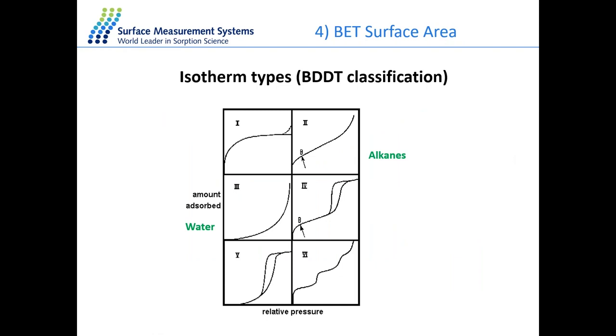Another thing that we can do with the DVS is to understand BET surface area. In this case, with the DVS, we can either use water as a probe or alkanes or other vapor molecules as probes. With the DVS, we tend to focus on using alkanes to understand BET surface area because water may actually influence the sample and interact with the bulk of the sample, and therefore you wouldn't be able to get an accurate and reliable measurement and determination of the BET surface area. The DVS can understand a type 2 isotherm and a type 4 isotherm using alkanes.